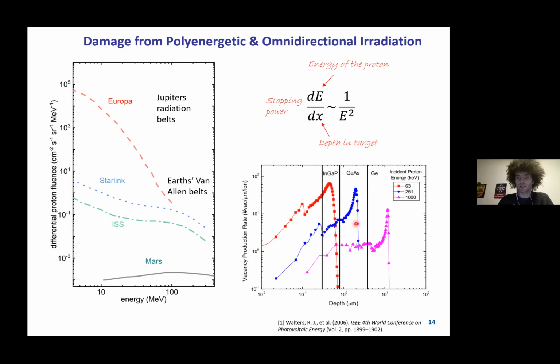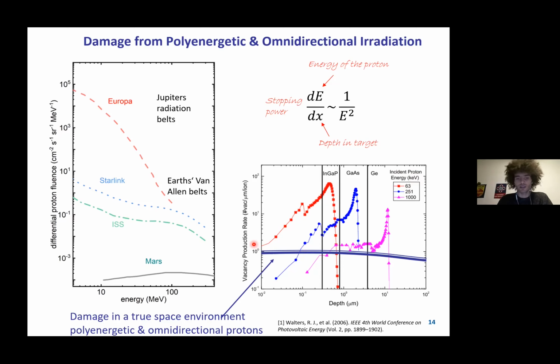And here I'm showing calculations for a triple junction solar cell, which was tested extensively with protons. And you can see quite nicely that, for example, 63 keV protons are only stopped in the top subcell and would only damage this. However, in space, we have a spectrum of protons with different energies, and they also come in different angles. And this then leads to very homogeneous damage throughout the entire solar cell, right?